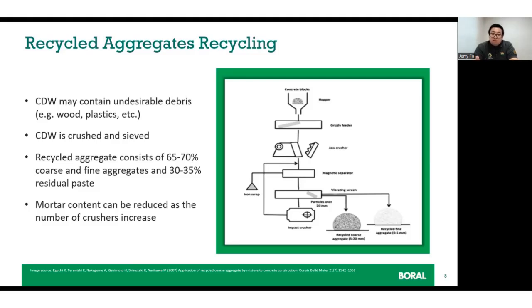The recycled aggregates produced at recycling plants may contain 65 to 70% coarse and fine aggregates, while the other 30 to 35% will be adhered old residual cement paste. The amount of mortar paste or cement paste is reduced as the number of crushers increases, but this usually incurs more production cost.